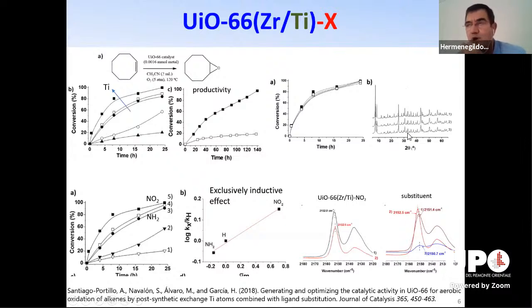I am stressing this because one of the main concerns in the case of MOFs is stability, and of course we always check. But I have to comment at this point that this reaction is carried out at not very high temperature, 120 degrees, with convenient solvents that are not corrosive, like acetonitrile. And under these conditions, UiO66 is very, very stable. You can reuse it, I don't know, 100 times without any change, and we did. Here, when you change the linker, and we can introduce an amino linker, or we can have just the proton or the nitro, the activity increases.